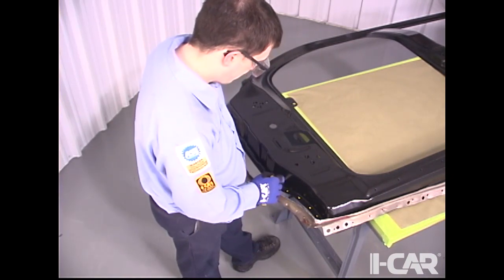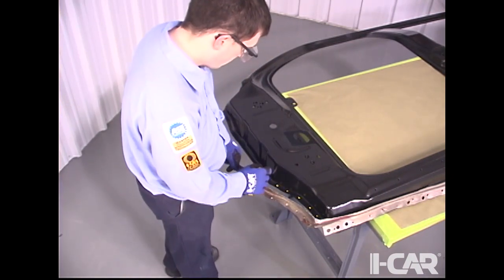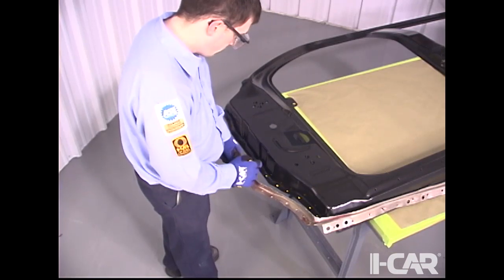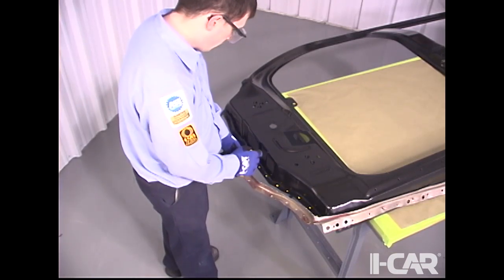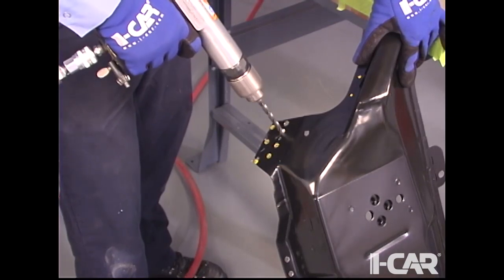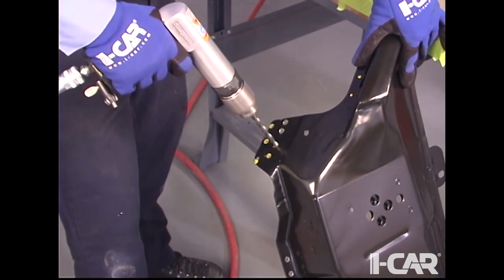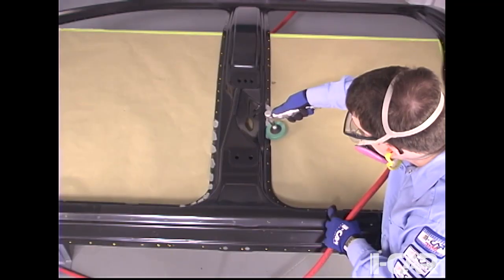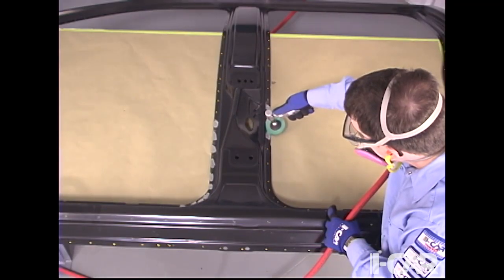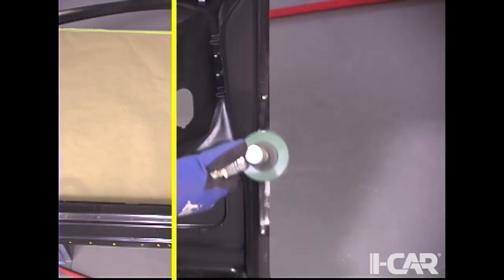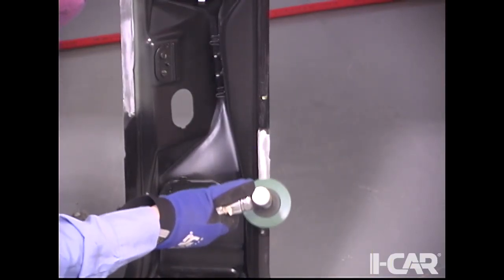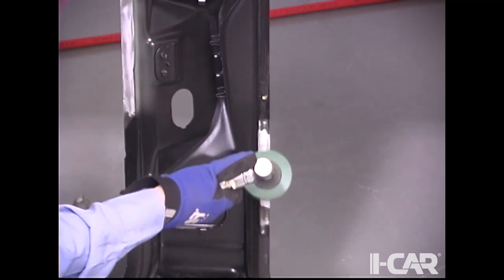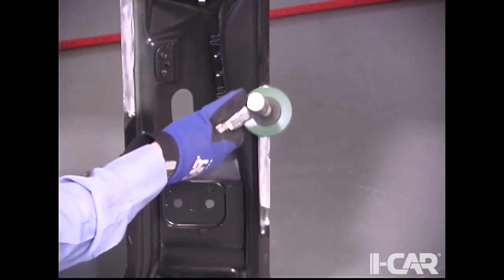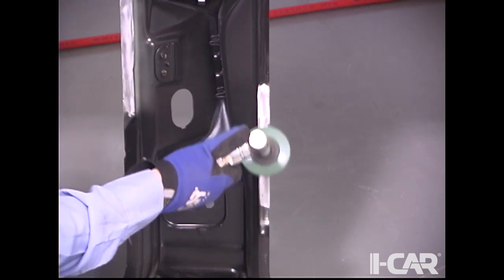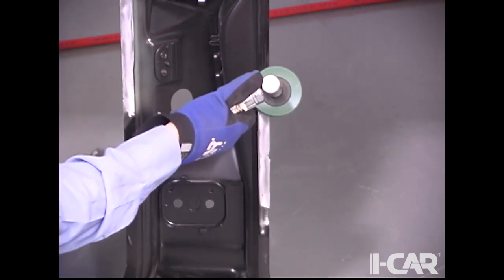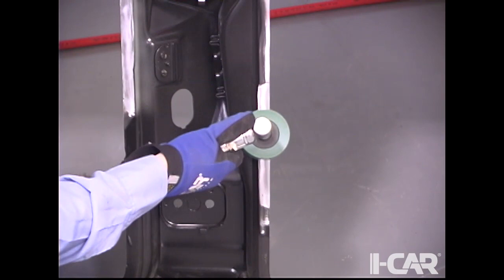To prepare the front edge of this panel for GMA MIG plug welds, the damaged part is used to reference the location of the original welds. Ford recommends using plug weld holes that are 8 mm or 5/16 inch in diameter. The E-coat is removed from both sides of the panel where the spot welds will be located. Next, the coatings at the bonding area of the flange are removed, including the galvanized coating. A shiny appearance indicates the galvanizing has been removed. A dull appearance means that galvanizing still remains and additional grinding is necessary.